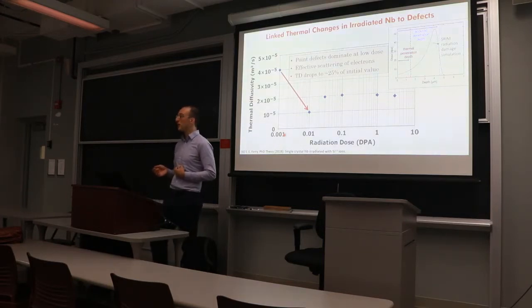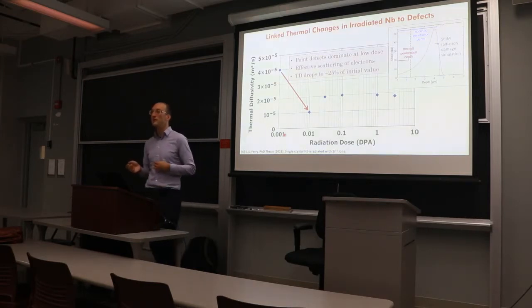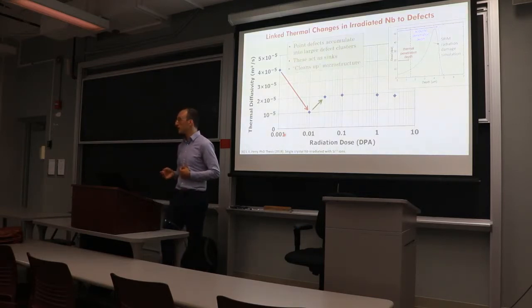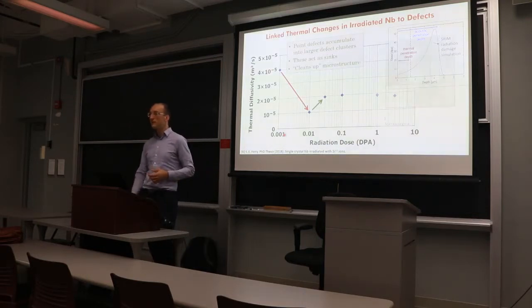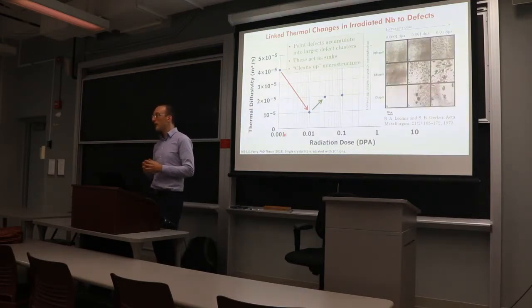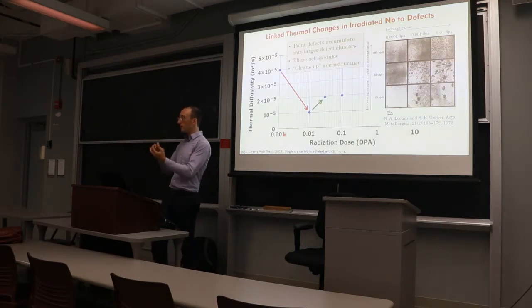And this is due to lots of point defect creation, and those point defects aren't very mobile in a high melting point material like niobium. With further irradiation at room temperature, the thermal diffusivity recovers to about half its original value, because TEM experiments show that these defects cluster together, and if you have more point defects in fewer big blobs, they don't scatter the electrons responsible for thermal transport as much, and the thermal diffusivity gets better.